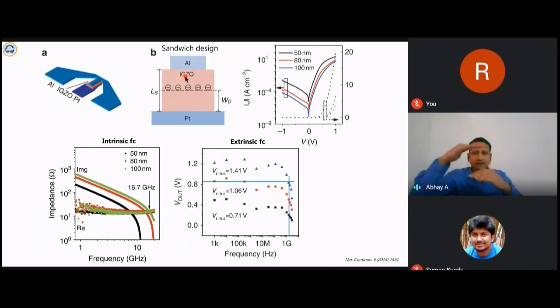So by changing the thickness of the semiconductor, we can change the device performance as shown here. For a thinner semiconductor, we will get a larger current, and vice versa. This is the impedance graph plotted as a function of frequency for various thicknesses. You can see for 50 nanometer film thickness, the cutoff frequency is around 8 gigahertz. But if the thickness goes to 100 nanometer, that cutoff frequency goes to 16.7 gigahertz.